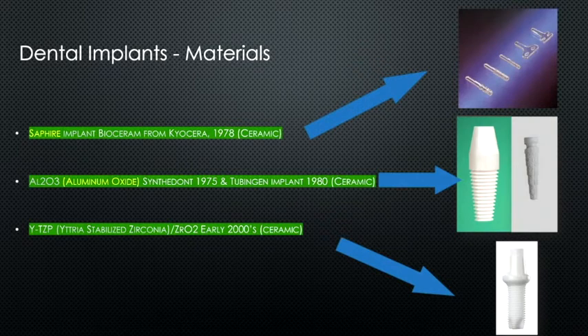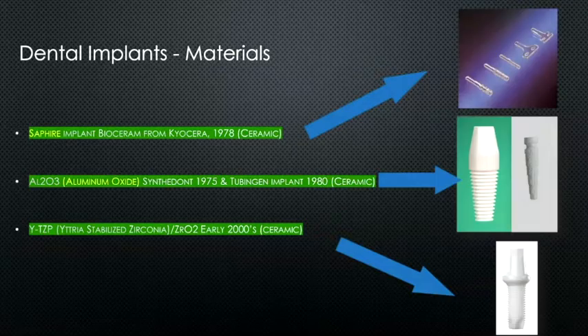And the problem with glassy implants, especially in bone, is rough surfaces. If the surface is as smooth as your glass or a bottle, osseointegration is very poor and the failure rate is high. Also, because it's clear like that, it's called glassy ceramics. Glassy ceramics are very weak. They tend to fracture. And it's monocrystalline also. It's one crystal. Then you have aluminum oxide also, which is a monocrystal. And I'll explain what I mean by monocrystal a little later.